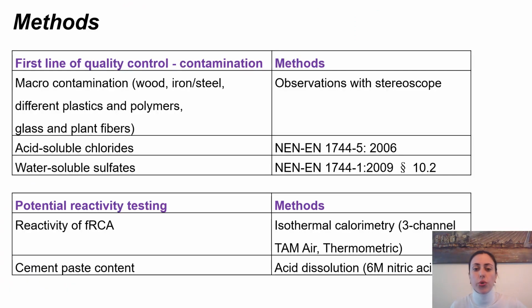The methods that were used: the first line of quality control is just visual contamination, and then the chemical analysis, considering acid soluble chlorides and water soluble sulfates, as we always regard these as the major contaminants in concrete and in the environment. And of course to test the potential reactivity of the fine recycled concrete aggregates, which is very important because many studies and also practical experiences have reported that in these fine recycled concrete aggregates there is a potential to partially replace cement or to be used as a filler, not only as a sand. We will see if this is the case for the studied Dutch recycled concrete aggregate.